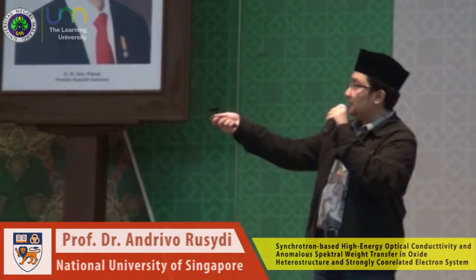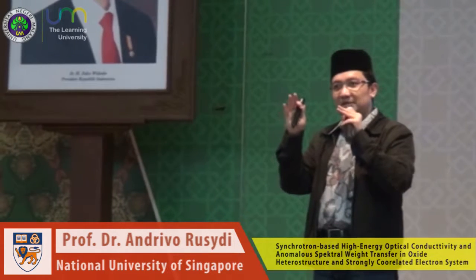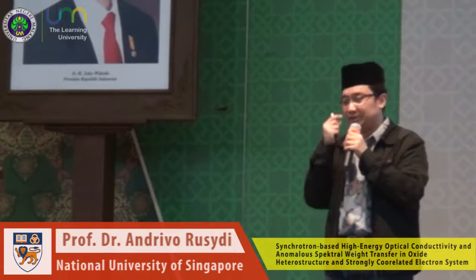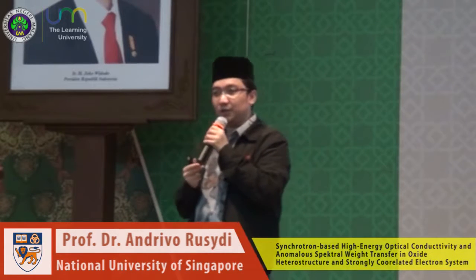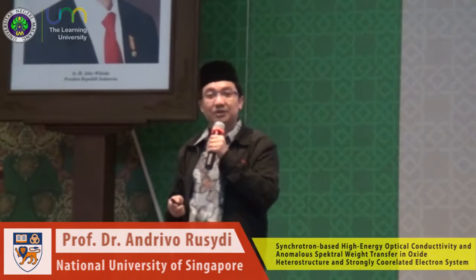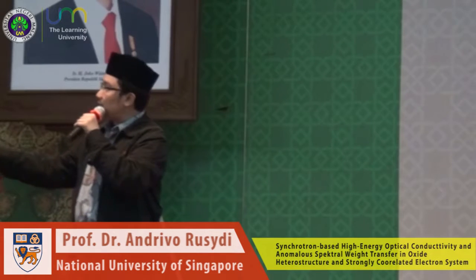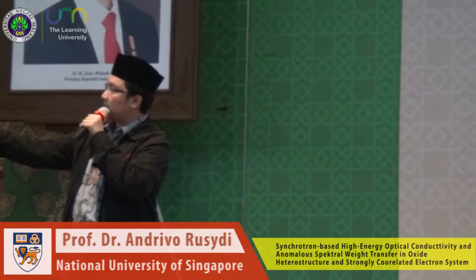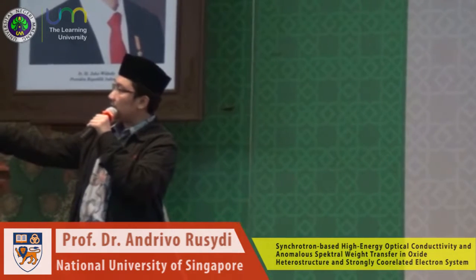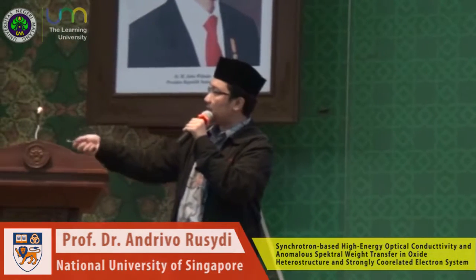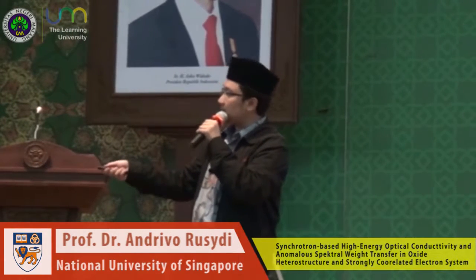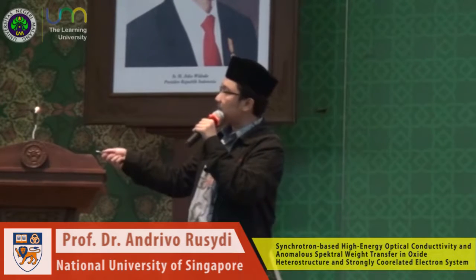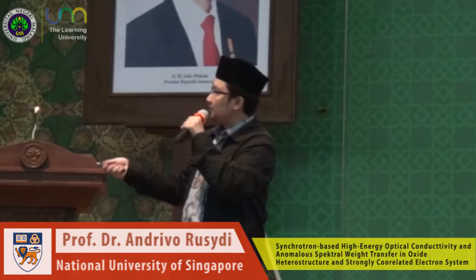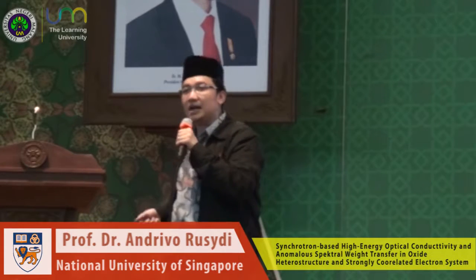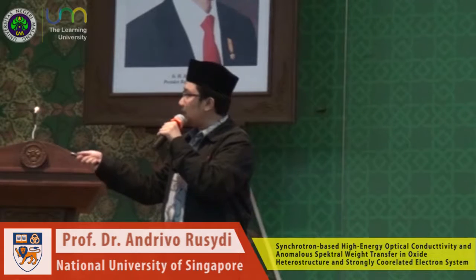And then we look carefully at strontium titanate, something that has been studied for more than 60 years. But this time we want to find out what we call the exciton, to see whether the exciton is really absent. Then we look carefully again at the optical conductivity. This is epsilon 1, epsilon 2. Epsilon 1 is the real part of the optical conductivity, and this is the imaginary part. And then this is the difference between the real part and the imaginary part as a function of temperature. And then we perform the theoretical calculations. So experiment 1, 2, 3 are experimental data, compared with theoretical calculations.